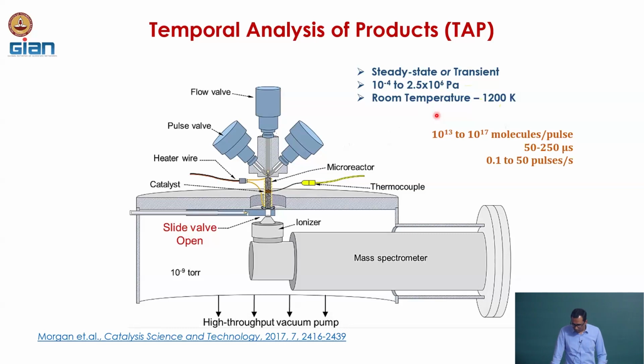Okay, I will just give the answer. It is roughly 10 to the power 15 atoms per centimeter squared, and we are pulsing 10 to the power 13 molecules. So, now look at the total number of sites that is available, and the amount of reactant that we are pulsing in is 1% of that, and on top of that the adsorption is not 100%. So, taking an efficiency of 10%, there is actually a 3 orders of magnitude difference between the number of sites occupied with one pulse and the total number of sites that is available.